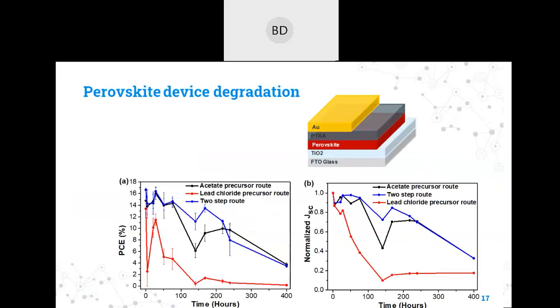Then we implemented all these three films in a perovskite device. We used TiO2 as an electron transporting layer and PTAA as a hole transporting material. With this device, we came to understand that even in the device itself, the perovskite is degrading faster. Even after 100 hours of exposure, the perovskite of the lead chloride route has degraded significantly, but the other two routes show significant efficiency.